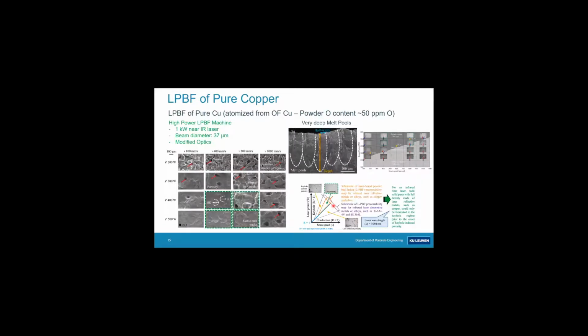Something I should mention here, we used a relatively broad laser beam of 60 micrometer, but we observed some optical damage in the optical system of the laser powder bed fusion machine due to back reflection. What we did then is we modified the beam diameter to focus the energy input more. We also modified the optics so that the back reflection was not directly shining on the mirror, and that is thanks to the help of the people of the mechanical engineering department. And then you notice that you could successfully process copper at a lower power level of 500 watts and a scan speed of about maximum 800 millimeter per second.